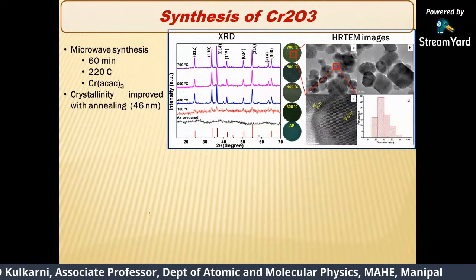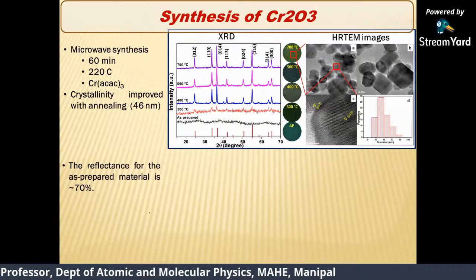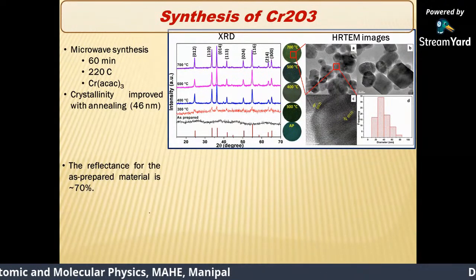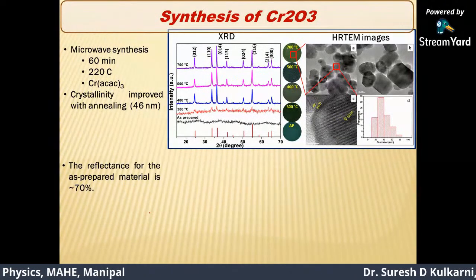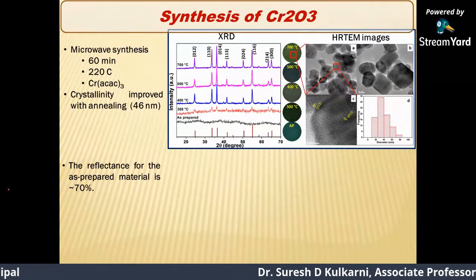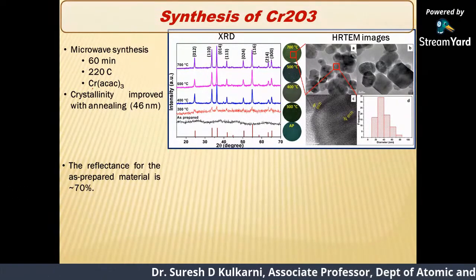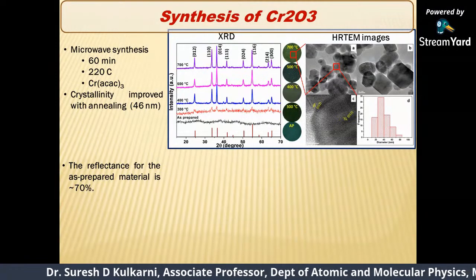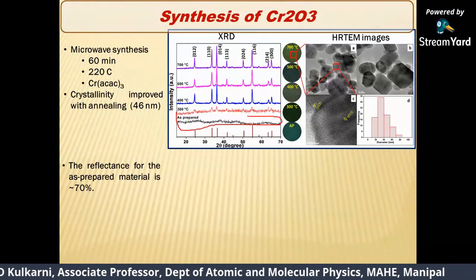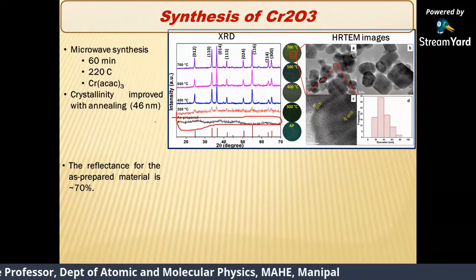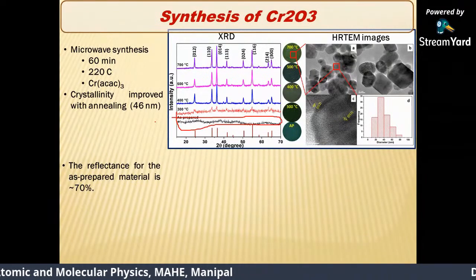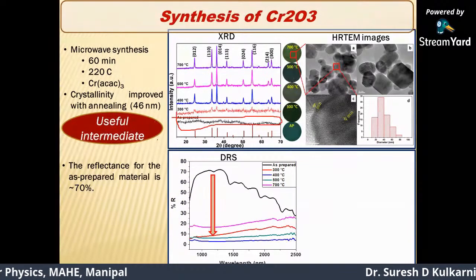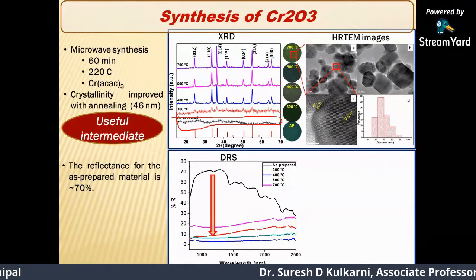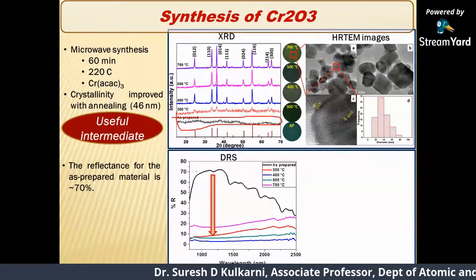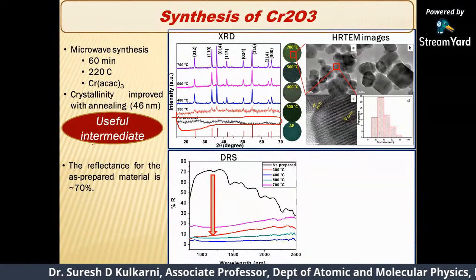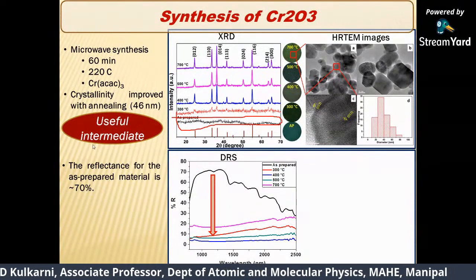Nice particles are formed, single crystalline in nature. But the important thing I would like to share is that during the 60 minutes of microwave synthesis, we get some intermediate product, which I am representing here. By XRD, I am not able to understand what this material is. But when we did a reflectance spectrum, you can see it is showing more than 70% reflection. So we started finding out whether this is a useful material.